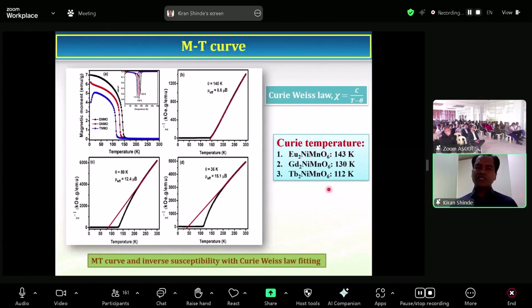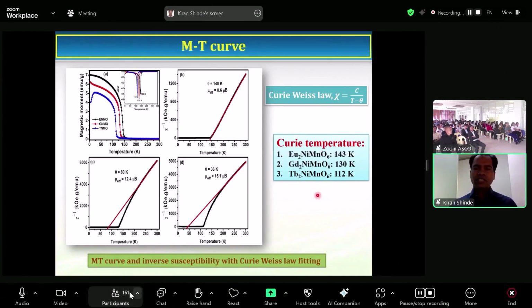So actually, when we are using this kind of material for application purposes, we have to focus on the working temperature. Like if we want to use this material for room temperature application, then room temperature is 300 Kelvin, so we have to find out or tune the Curie temperature of the material to room temperature. If we are working in the cryogenic temperature region like 20 Kelvin, then we have to tune the Curie temperature or find a new material having the Curie temperature particularly at that working temperature. So we are trying to check the effect of the different A-site element in the double perovskite and how it affects the magnetic property, MCE property, and how we can tune the Curie temperature. So if we change this A-site element, then we found there is a drastic change in the Curie temperature.